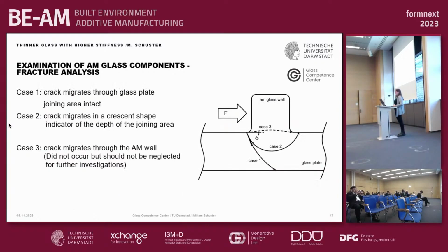And here, this is very interesting in my opinion. So we expected 3 different failure modes. The first one would be that the crack migrates through the glass plate. The second one, the crack migrates in a crescent shape. And the third mode would be that the crack migrates through the AM glass wall. And actually, in our test, case 3 did not occur yet. So I think in those 10 tests that we did, we had a very good connection between the AM wall and the base plate.